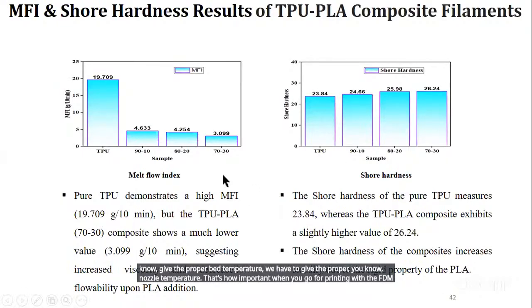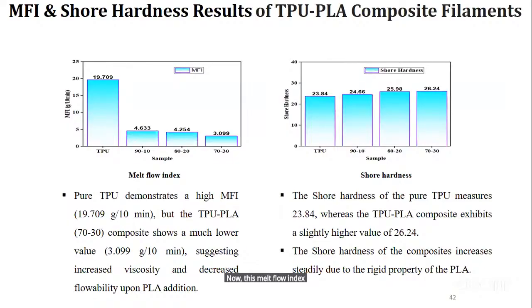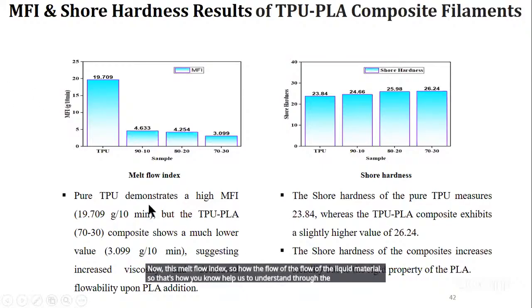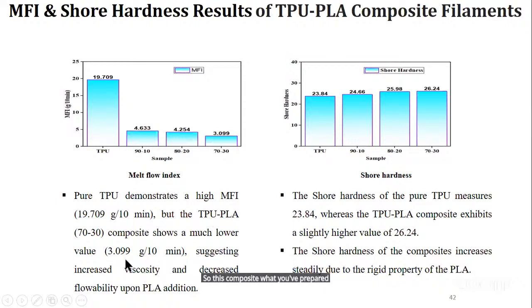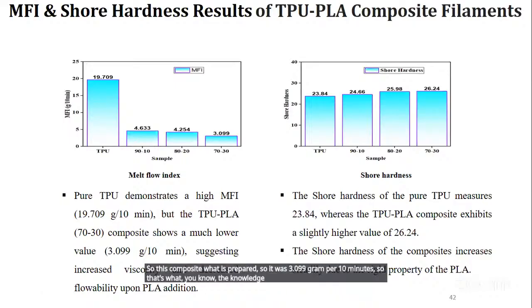Now there's the melt flow index, which is about how the liquid material flows. That's how it helps us understand through the MFI. Pure TPU demonstrates a high MFI of 19.709 grams per 10 minutes. For this composite that we prepared, it was 3.099 grams per 10 minutes. So that's the knowledge we have gathered through the MFI.